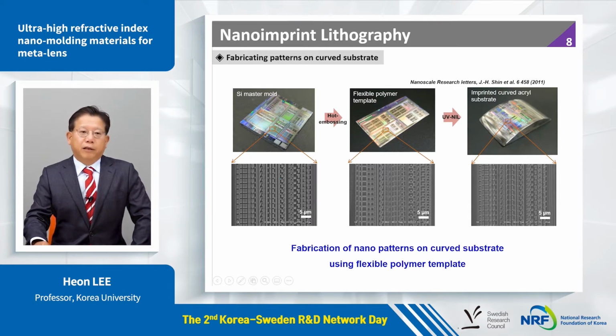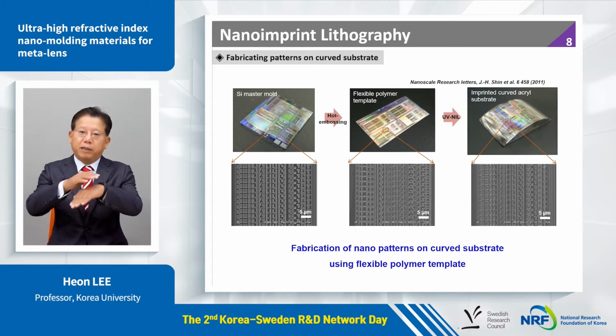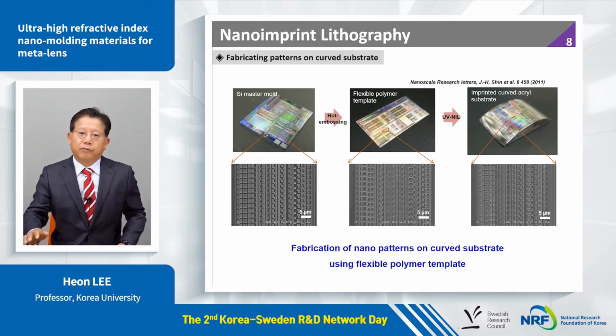Well, this is a silicon mold containing a surface protrusion pattern. We can transfer this nano pattern to a flexible polymer. Then, using this flexible polymer, we can transfer this nano pattern to a non-flat surface. Because nanoimprint lithography is not an optical process, by simple physical contact, we can transfer the nano pattern onto a non-flat surface.